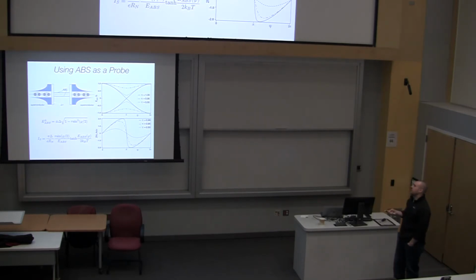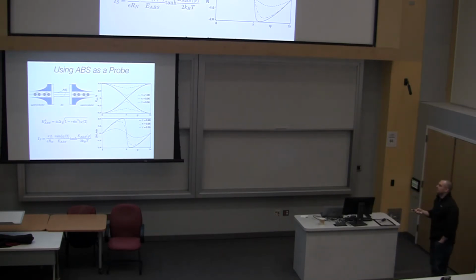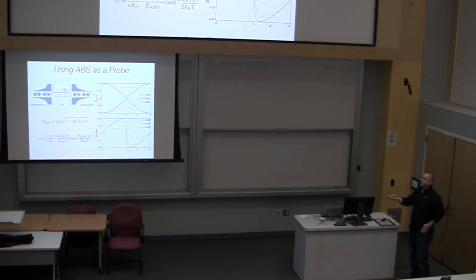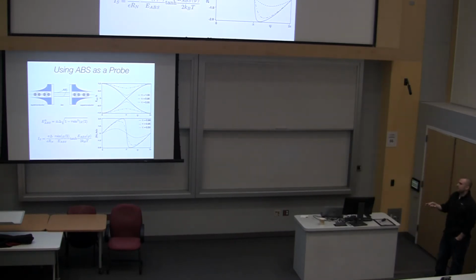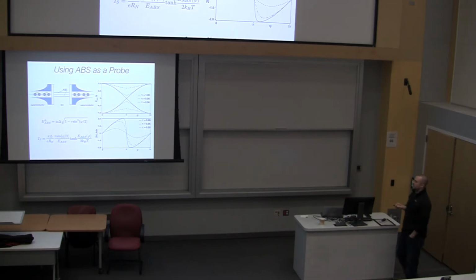And what I want to look at is the evolution of these energies of these Andreev bound states as a function of something that was called tau, which is generically the transmission probability that you make it, say, from a Cooper pair being over here to a Cooper pair being over there. So it really has to do with both the transparency of the interfaces, but also the quality of the material. Are you ballistic or diffusive within that material?